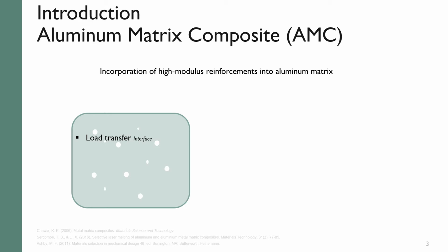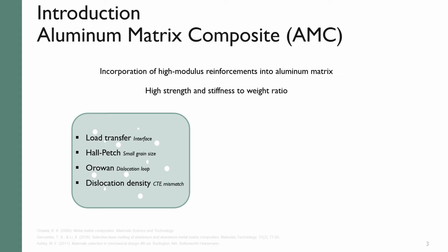through the interface from matrix to ceramic reinforcement, Hall-Petch strengthening thanks to smaller grain size, Orowan strengthening due to dislocation looping around the ceramic particles, and increased dislocation density because of the coefficient of thermal expansion mismatch. And all of these allow high strength and stiffness to weight ratio.